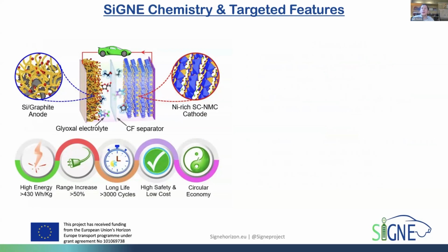In terms of our overall cell architecture or cell design, you see at the anode side, we have a silicon nanowire graphite anode material that you'll see here. We're looking at a range of different electrolyte components, but glyoxal-based is the driver on this. It's a paper-based separator that we have, and then it's a nickel-rich single crystal NMC where it's cobalt poor. So we're talking about 4% cobalt is the indicative range of cobalt within that. These are our targets then.